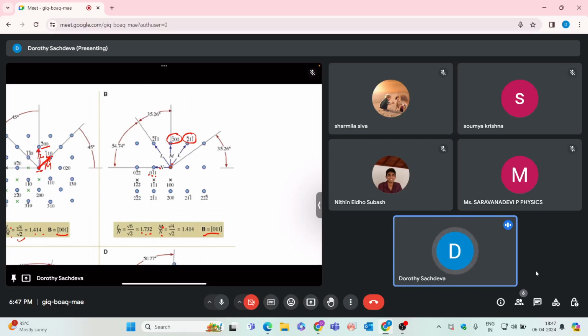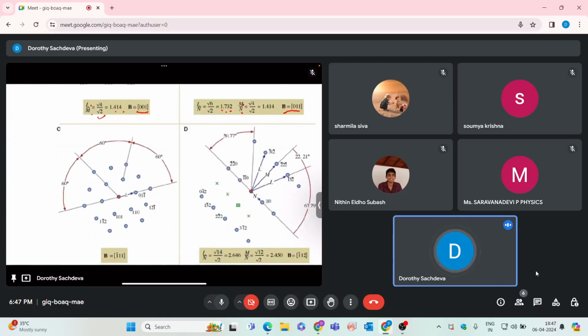Also you need to see the angles as well as the distance. So firstly, you have this diffraction pattern. You will calculate the distance of these two non-linear vectors, either NM or ML or NL. You can find out NL, ML, NM, because all three have different angles and all are non-linear. So you need to calculate the distance and the angle between these two. So if all these satisfy, you can just practice for the standard samples. Like the third one is bar 1, 1, 0.